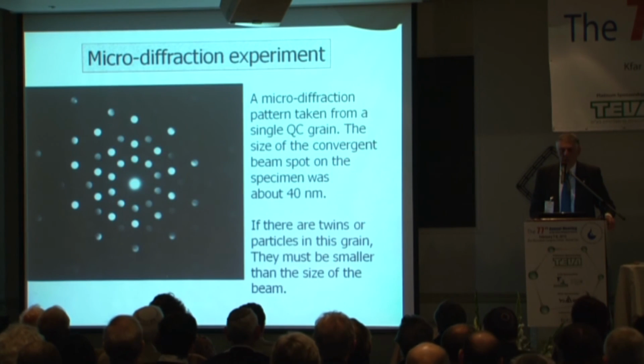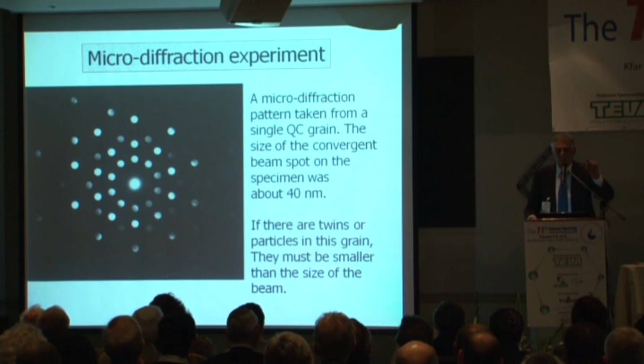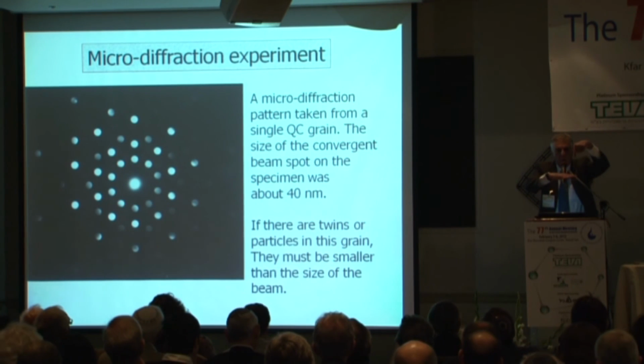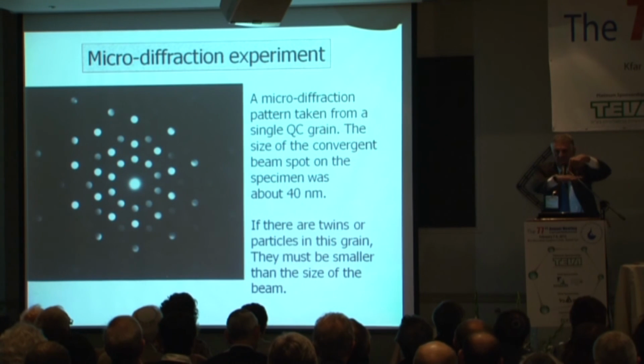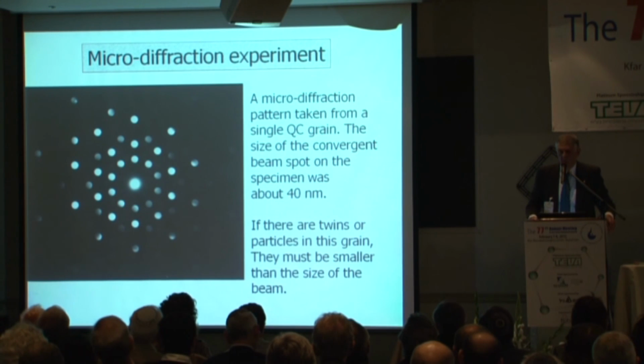And the diffraction pattern that emerges there was that. Everywhere I went on the crystal, with the convergent beam, you move your crystal under it, from grain to grain, it was always the same. And so down to 40 nanometers, no twins.